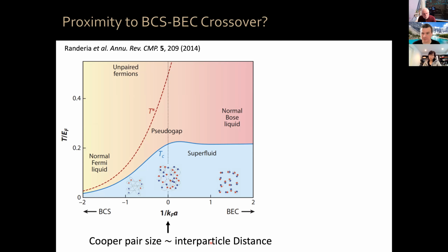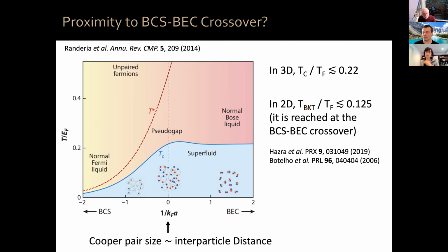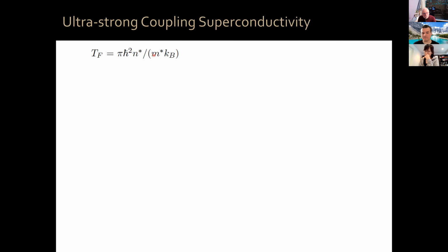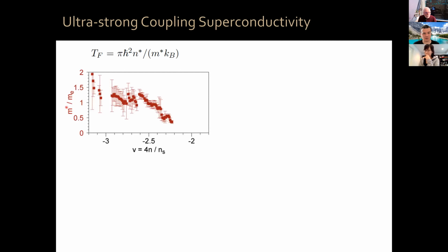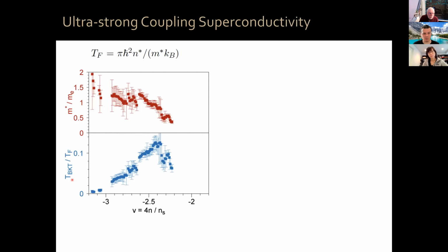Now, in 3D there is a critical temperature over TF upper bound of 0.22. In 2 dimensions, it is a TBKT over TF upper bound of 0.125, which is reached at the BCS to BEC crossover. Because we can measure the effective mass and the density of our carriers, we can measure the Fermi temperature, and let me show you here the effective mass as a function of filling factor. We can also measure TBKT as I showed earlier, so we can plot TBKT over TF as a function of filling factor. You have this behavior. This is at optimal electric field.